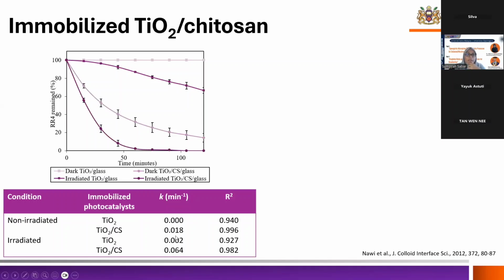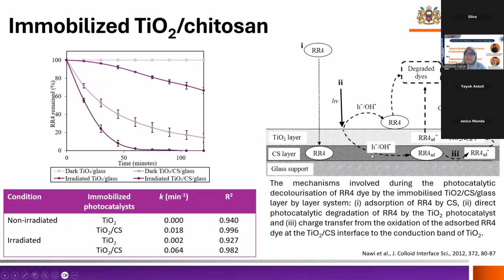So if you compare the rates of the photodegradation, you can see that the rate of titanium dioxide chitosan is about 32 times higher as compared to TiO2 alone. Okay. And this is the proposed mechanism that was involved during the photocatalytic decolorization of Reactive Red 4 dye. There are three main steps involved in this degradation. The first one is the direct adsorption of the dye onto the chitosan layer. So these dyes are not being degraded, they directly adsorb onto the chitosan layer.